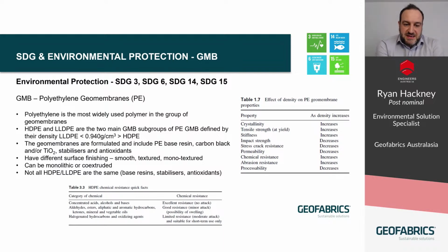The polyethylene geomembrane itself is actually a formulation, and it includes a polyethylene base resin, and then additives that are added to that to create a geomembrane. The additives include carbon black. When you see a black geomembrane, that's a result of the addition of 2 to 3% carbon black in the formulation. In the case of white geomembranes, it's the titanium dioxide pigment that colors the geomembrane white. In addition to those additives, we have stabilizers and antioxidants, and those actually protect that base resin from degradation. Again, on the next slide, we'll look into how we challenge the membranes to be sure of the service life in these different mining chemistries.